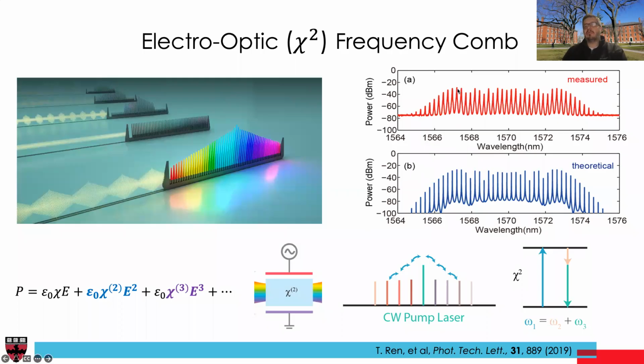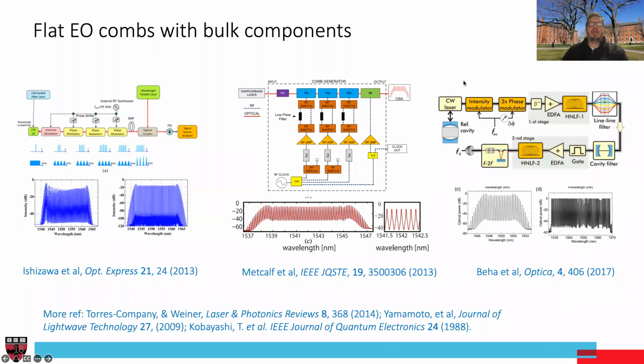One drawback of this approach was, as you can see here, that this comb wasn't flat. Depending on the application, it can be a problem or not an issue at all. For the envisioned application in telecom, where each of these comb lines that we generate would be an optical carrier, it's not good that some of these carriers are 15 dB or more suppressed than their neighbors. And for application in spectroscopy and many others, we would want these comb teeth to have the same strength. Fortunately, the community has recognized this shortcoming and proposed solutions.